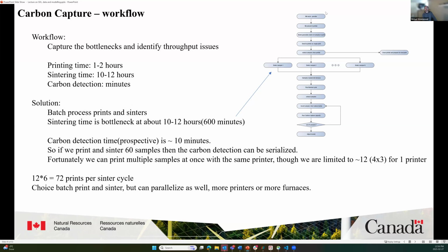So our basic workflow: we said, okay, what are our various processes and what are our bottlenecks? Our printing time is 1 to 2 hours, sintering time is 10 to 12 hours, and carbon detection, assuming our in situ system works, will be on the order of minutes. I know that the full cycle where they do direct air capture, or sorry, point source capture at least, has a cycle time of just 3 minutes. So that's where I'm pulling the minutes from, but if we could do it in situ, we might even be able to do it faster than minutes.